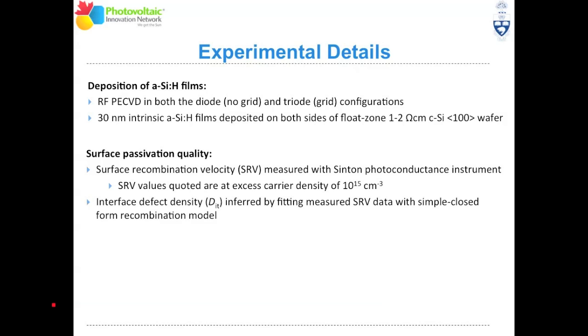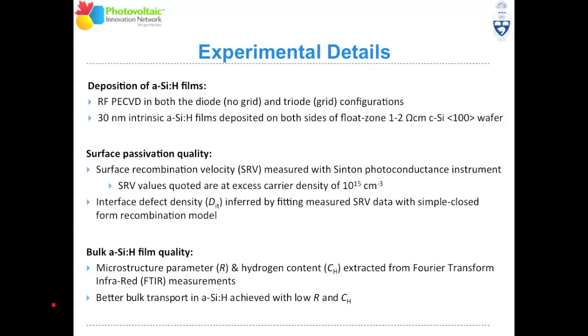And we also were able to deduce the interface defect density through the surface recombination velocities that are measured. In addition to measuring the passivation quality, it was really important for us to also know what the bulk film quality was, because although the passivation quality is really important in the silicon heterojunction solar cell, so is the bulk amorphous silicon film properties, because the carriers that are generated in the crystalline silicon wafers still have to be transported through the hydrogenated amorphous silicon film.